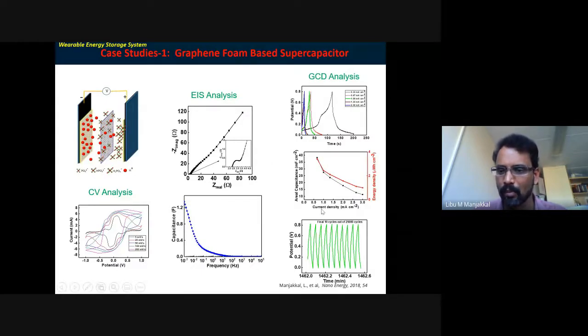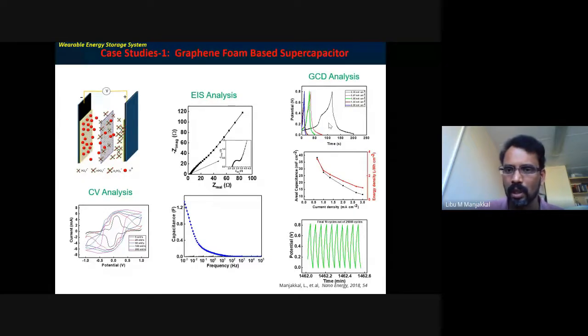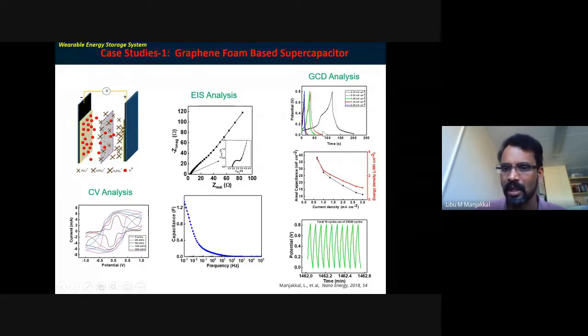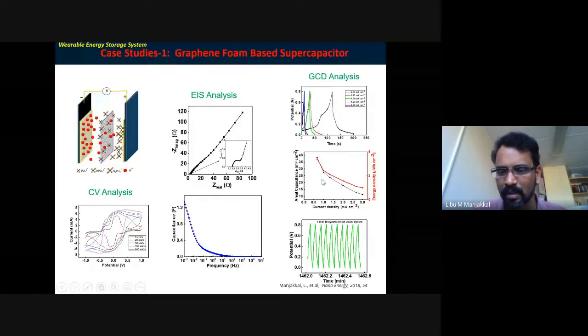And then I measured the device with GCD, which means galvanostatic charging discharging analysis. In our mobile phone, we charge the phone fully to 3 volt or 4.2 volt. Here I used 0.8 volt. Once we fully charge, then we discharge it through normal operation. This is like that. When you charge your device fully and then discharge normally, it measures the full performance of our device. And I calculated how much energy density my device can provide, and the life cycle.